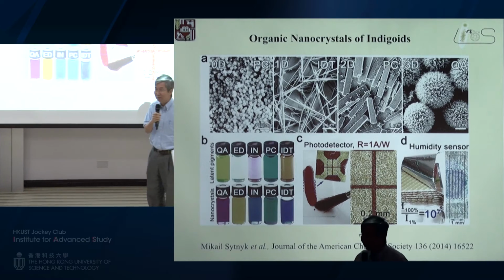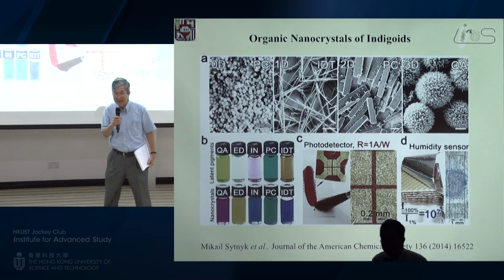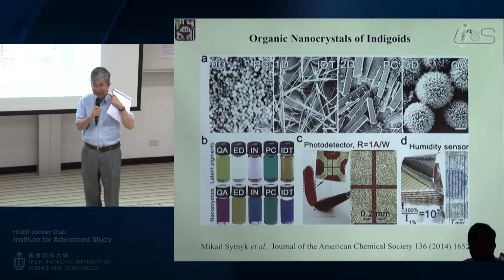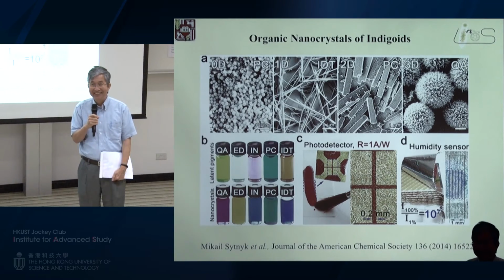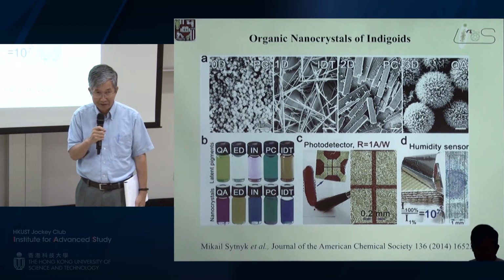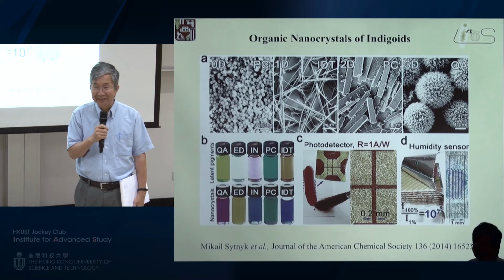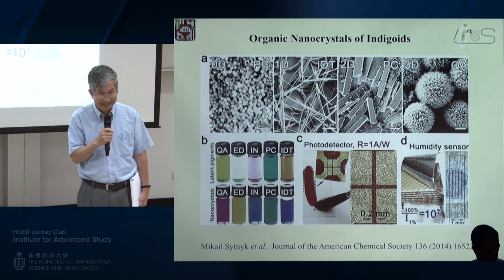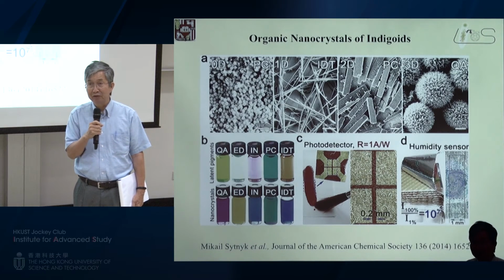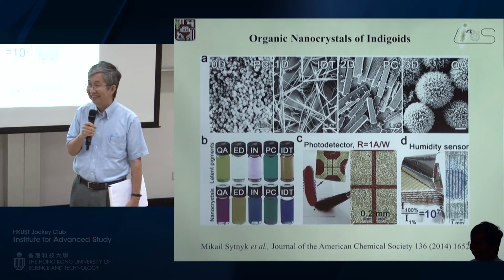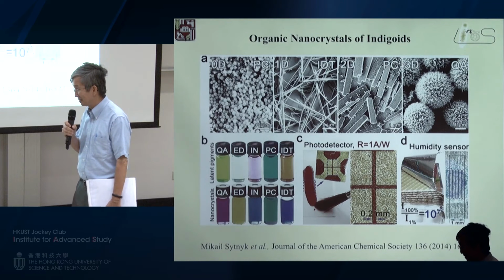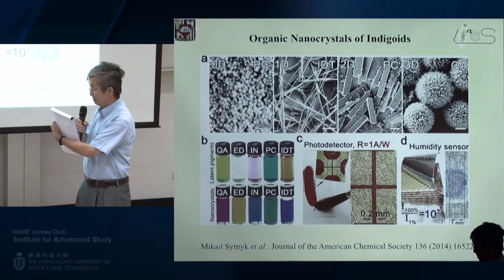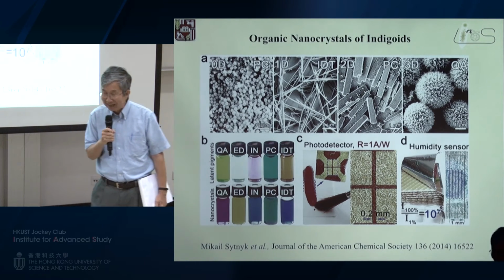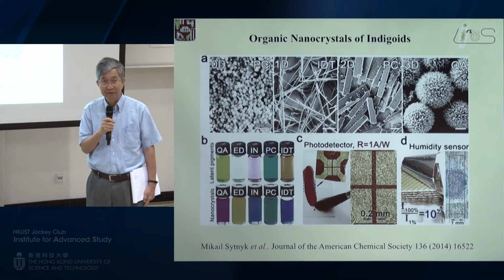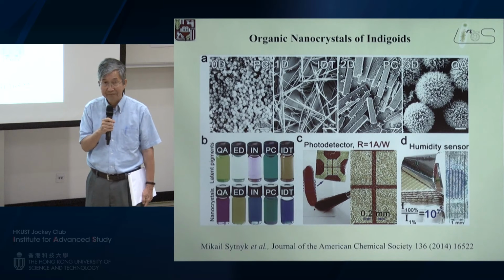Interesting, Michael, this hydrogen bonding. I may have something to add to it. The discovery of organic light-emitting diodes at Kodak was based on a compound that has hydrogen bonding. And I will disclose it for the first time in Guangzhou next week. The way to get rid of the hydrogen bonding, which I did some 40 years ago, was to cool it in liquid nitrogen. So you freeze it. I actually used the same compound, the indigo kind of compound, for light emission. And actually the compound is in your slide, I was very surprised. And it actually worked. You can get very high efficiencies, almost 30 times higher compared to room temperature. And it's reasonably stable, light emission.